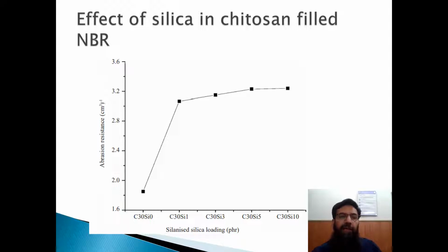Similarly, the effect of the silica can also be seen on the abrasion index. With the increase in loading of the silica, abrasion index of the rubber increases. Here in this case, up to 1 pHr, we get the increase in the abrasion resistance of the chitosan filled NBR. But if we further increase the loading of the silica, there is not sufficient change in the abrasion index, and it makes a plateau. So up to 1 pHr, we can say there is a maximum increase in the abrasion index, and onward there is an increase, but that increase is not as much as compared to the up to 1 pHr.